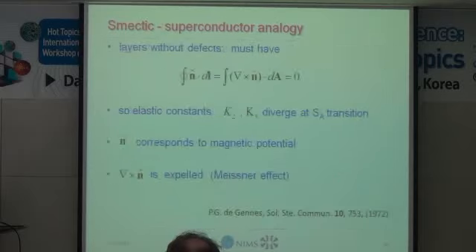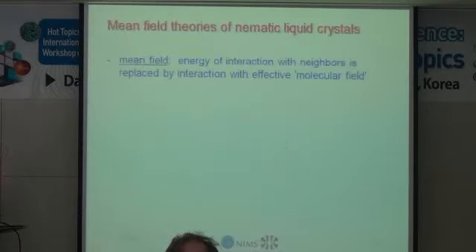And so then it follows that the curl of n must vanish inside the material. And in the elastic energy I showed you, there were two terms with the curl of n. And so in the smectic phase, that curl must vanish, so the elastic constants have to diverge as you go to the phase transition. So one sees the analogy of a superconducting transition, the divergence of these two elastic constants to expel the curl of n, which is like the Meissner effect.